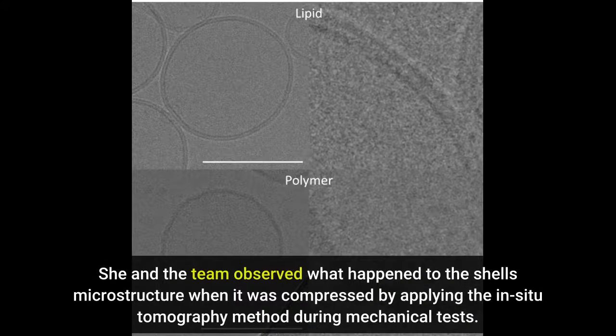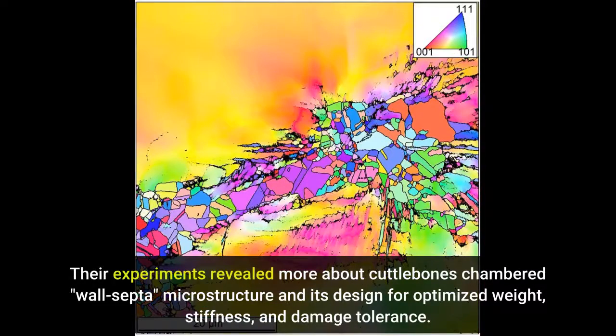Ph.D. student and study co-author Ting Yang used synchrotron-based microcomputed tomography to characterize Cuttlebone microstructure in 3D, penetrating the shell with a powerful X-ray beam from Argonne National Laboratory to produce high-resolution images. She and the team observed what happened to the shell's microstructure when it was compressed by applying the in situ tomography method during mechanical tests. Combining these steps with digital image correlation, which allows for frame-by-frame image comparison, they studied Cuttlebone's full deformation and fracture processes under loading. Their experiments revealed more about Cuttlebone's chambered, wall septa microstructure and its design for optimized weight, stiffness, and damage tolerance.